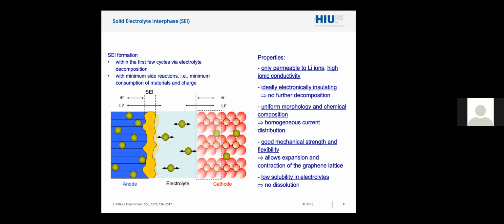If we don't have this homogeneous current distribution, then we will have hot spots, and this is definitely not good for performance, but also for safety. Very good mechanical strength and flexibility, allowing the expansion and contraction of the graphite and graphene lattices that occurs upon insertion and de-insertion of lithium. And it should be not soluble, or at least have an extremely low solubility in the electrolyte, because if it dissolves, then it needs to be reformed again, and this will consume charge.